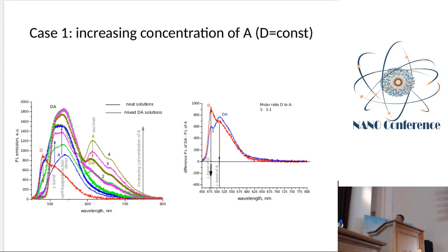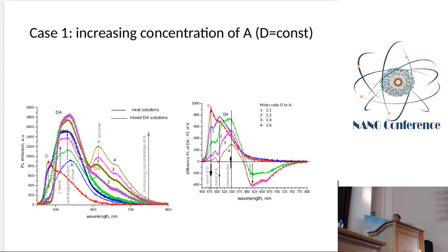We can see a spectrum of the donor emission and a spectrum of the donor emission in the presence of the acceptor when the molar ratio is 1:1. So we can see the quenching of the donor J-aggregates and increase of the acceptor J-aggregates. So energy is transferred from donor J-aggregates to acceptor J-aggregates, which is quite understandable. But when we increase the concentration of acceptor more in the solution, we have a qualitative change in this picture, because we observe a main enhancement of the spectrum located near 550 nanometers, which corresponds neither to J-aggregates of acceptor nor to dimer of acceptor.